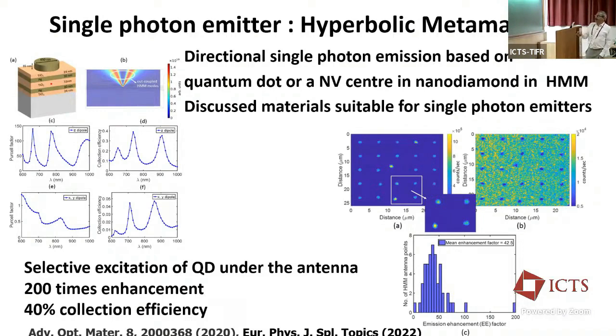So we optimized the structures. We did this with single quantum dots. These are cadmium sulfide selenide quantum dots, or we have NV nanodiamonds, with NVs in them. And we showed that we can get 200 times enhancement, and 40% collection efficiency is what we have reported.